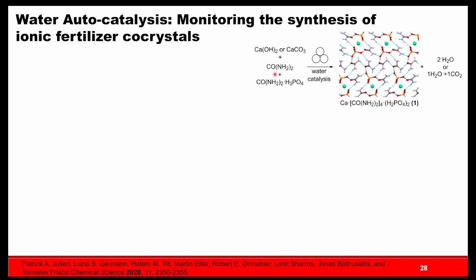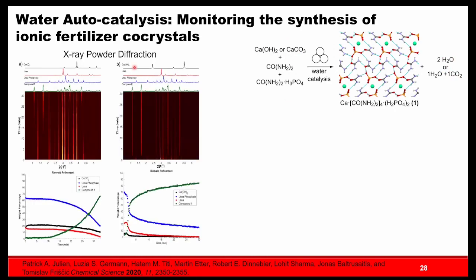So in this case, we're trying to make calcium urea phosphate. We're doing that by reacting either calcium hydroxide or calcium carbonate with an equivalent of urea as well as an equivalent of urea phosphate. When you make this, your byproducts are either going to be water, or water and one CO2 if you're starting from the carbonate. One thing that I was quite surprised by when we originally ran this is the X-ray powder diffraction data. It's a similar waterfall plot.